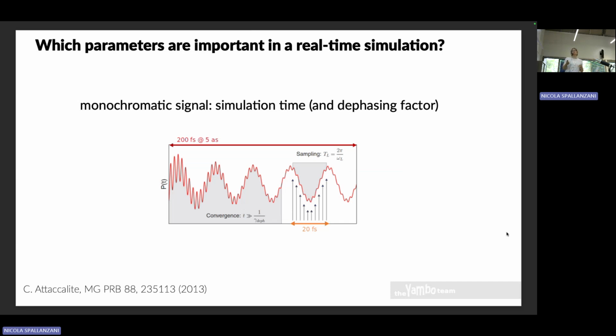So basically what you need to do is apply a phenomenological dephasing, and then you just wait until the eigenfrequencies are negligible with respect to the signal of interest, so second harmonic and third harmonic. Then you take one period and you sum, and then you sample your signal there.